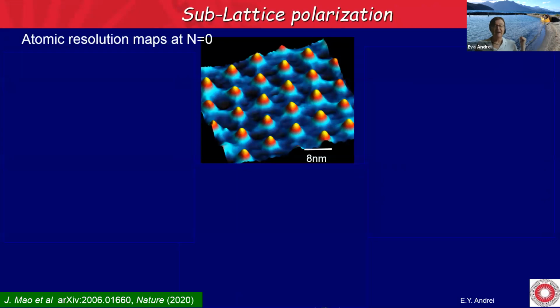Now, in terms of the sublattice polarization, we're going to go to atomic resolution map in the n equals 0 level. And if you remember, the wave function, the K point lies on the A sublattice and the K prime point lies in the B sublattice. Here we have the pseudomagnetic field is 108 Tesla, and around here it is much smaller. It's around something like 50 Tesla, because the area is much larger.